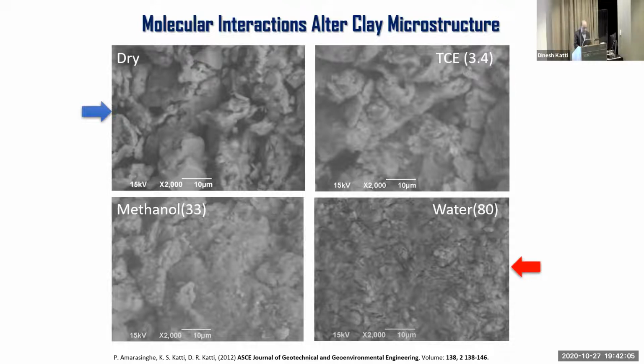Okay. Now, when you go up and look at the same clay through which TCE, which is a non-polar fluid, when that passes through, if you compare that image with the image to the left of it, you will see that those 2 images look very similar. And why do those images look very similar? Because TCE does not interact with the clay, and because of which there is no change in microstructure. And what you see more importantly here in the image on the right-hand side top is you are seeing large void spaces and large particle sizes. So that's why TCE flows 500,000 times faster through the clay than water. And that's the reason for that.